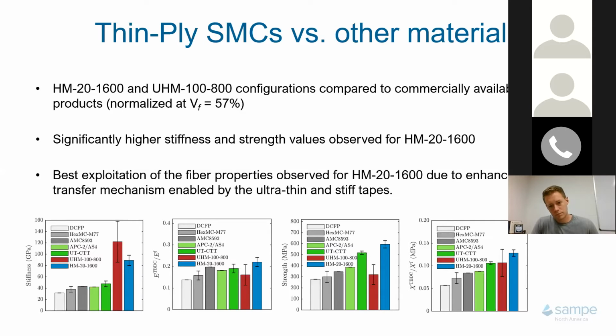The fiber volume fraction, I have the same answer here. Since it's different material systems, the fiber volume fraction was not the same, but every result was normalized with a fiber volume fraction of 57%, that is typically seen in the SMC products.